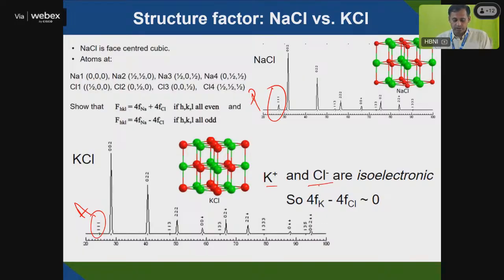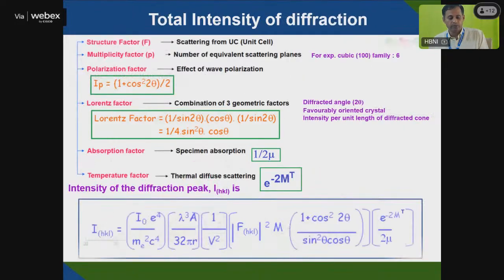That is mainly because of the isoelectronic nature of K and Cl. They are isoelectronic, so the scattering factor coming from this F, the 4K will come from the K atom and the 4Cl will come from the Cl, they will be equal and they will cancel out, and you'll get 0. Because they are isoelectronic, they cancel. But in the case of NaCl, there is 4Na minus 4Cl, so there is a net contribution present and you get a small peak, but here it is absent. So that's why you are not getting the KCl peak.